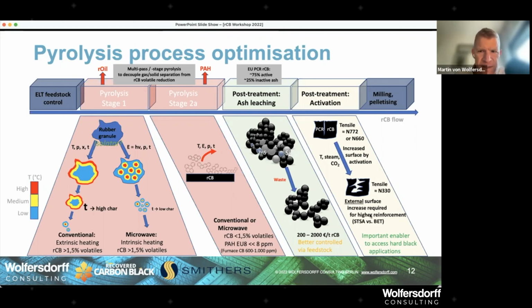Post-treatment, there's also activation, which is also not industrialized, but the concept is that you could get higher reinforcement by increasing the surface area to a surface area which is closer to reinforcing carbon blacks. And then, of course, we have to mill and pelletize.